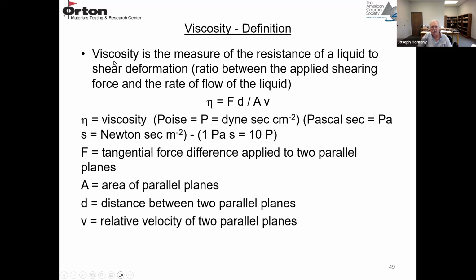So the glass composition controls the viscosity along with the temperature. So viscosity is important for high temperature hot strength, for creep resistance, and for other properties like corrosion resistance and thermal shock resistance. So viscosity is simply a measure of the resistance of a liquid to shear deformation. So it's the ratio between the applied shearing force and the rate of flow of the liquid. So eta is the viscosity, and the units are poise or Pascal seconds. So poise would be P, and that's dynes second per square centimeters. A Pascal second is Pa·s, that's Pascal times second. It's actually a Newton second per meter squared. It turns out that 1 Pascal second just equals 10 poise.